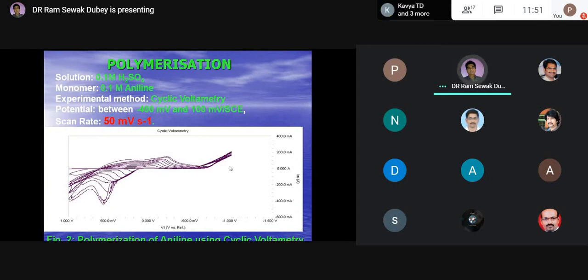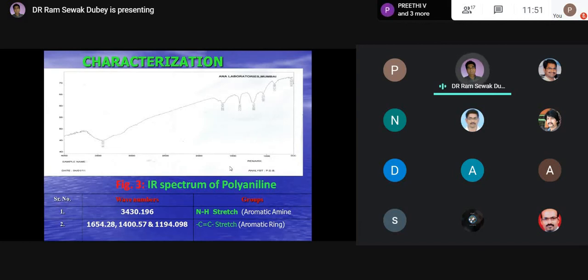The final product deposited on the surface was purified and characterized with the help of other techniques also. The IR spectrum of polyaniline is shown here. The peak at wave number 3430 is assigned to N-H stretching of aromatic amines, and the peaks 1654, 1400, 1194 can be assigned to carbon double bond carbon stretching. Similarly, peaks at 1053 and 886.55 are assigned to C-H bending.